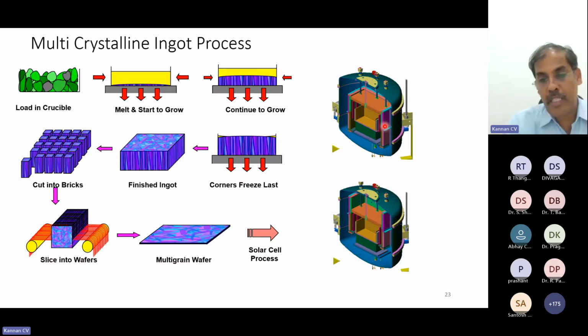And what is happening right now is multi-crystalline. Another improvement in multi-crystalline is, instead of only a crucible, they put some monocrystalline seed, a monocrystalline brick, at the bottom of the crucible. Then whatever crystal initiates from the monocrystalline bottom seed, the quality of the wafer will be relatively better than multicrystalline. It will be in between pure monocrystalline grown by the Czochralski process and multicrystalline grown by DSS. That's mono-like multi.